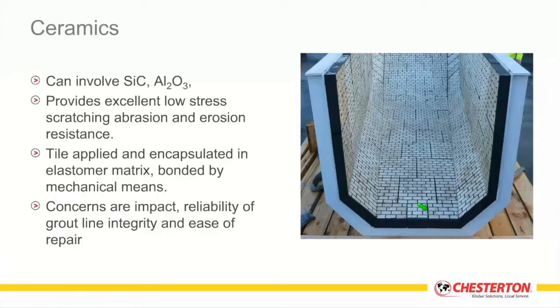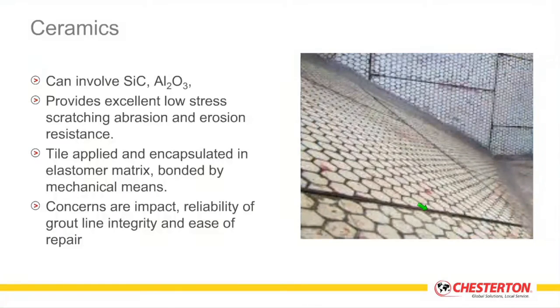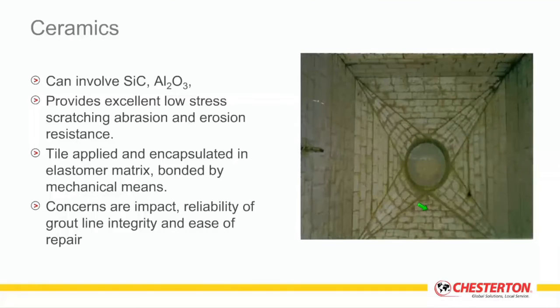Where you do have high impact applications, there the ceramic tile is often embedded into a rubber matrix, so the rubber can actually absorb the high impact stress while the ceramic provides wear resistance. And here you can see some examples of the ceramic tiles that are used. You can see it comes in square shapes, it comes in hexagonal shapes. It may be applied in different contours where you're going from square to round transitions, so the labor intensity of this type of application is quite high. The installed cost is quite high. But in those applications where you're dealing predominantly with sliding abrasion, low angle of impact sliding abrasion, ceramic systems are quite popular.